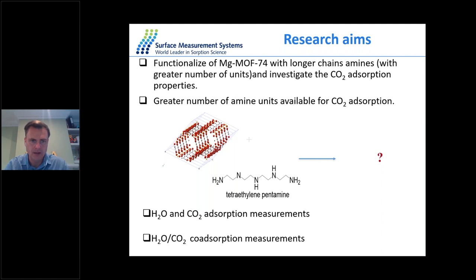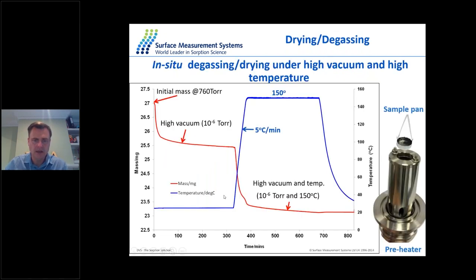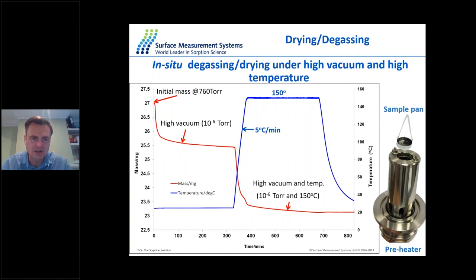We focus on magnesium MOF-74, one of the first MOFs reported for CO2 capture due to its high adsorption capacity. We want to increase the number of sites available for CO2 adsorption by functionalizing magnesium MOF-74 with ethylenediamine and pentamine. Before discussing the results, I want to highlight one of the powerful capabilities of DVS: it can monitor in real time the outgassing of the material. Here we look at a MOF that was initially outgassed using only high vacuum at 10⁻⁶ Torr.